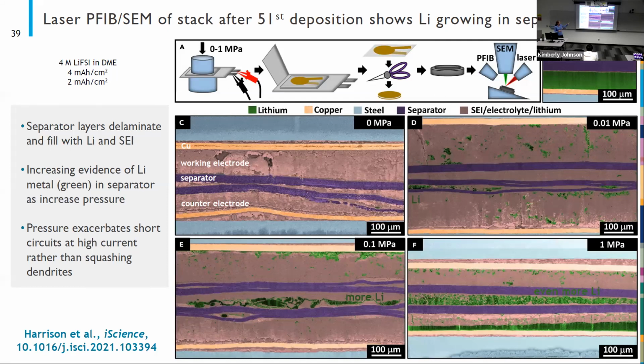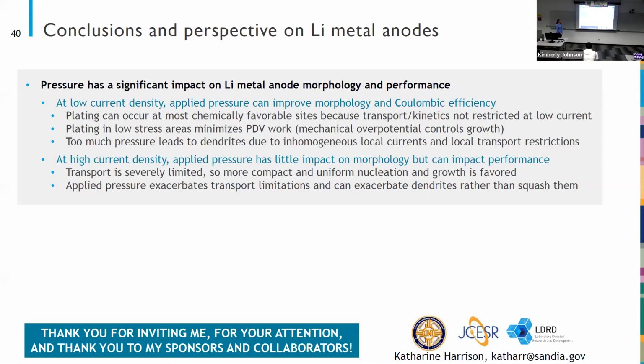And what you can see is that as we increase pressure, we get more and more lithium growing into the separator. So this really goes with the theory that the pressure is exacerbating short circuits. It's causing us to grow lithium into the separator. And increasing pressure when we have current is probably not a good idea because it exacerbates the transport problems and causes shorts. So that's all I've got.